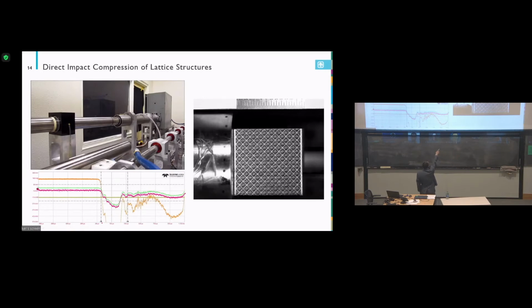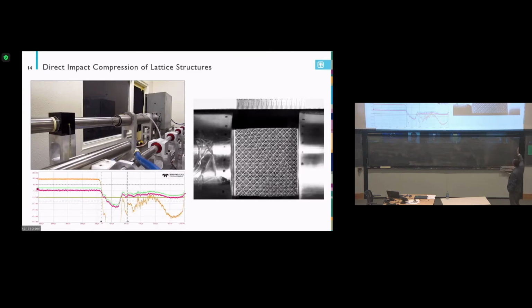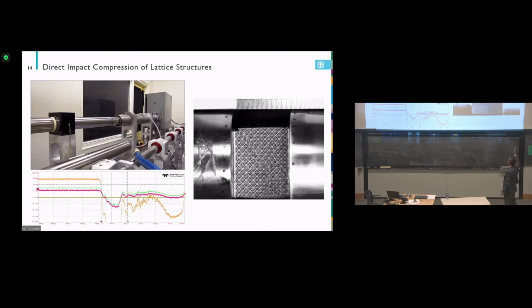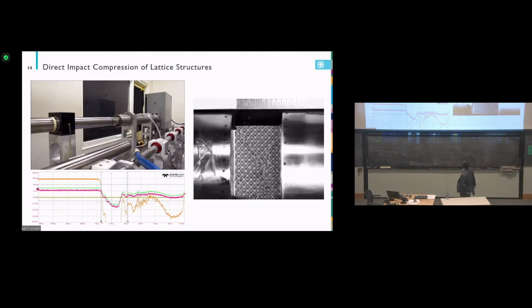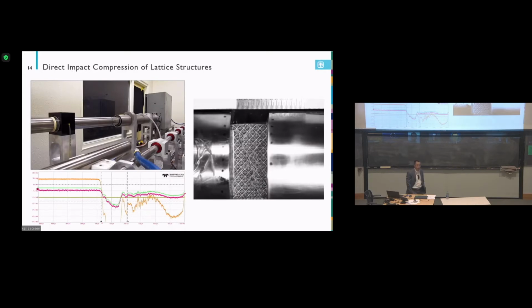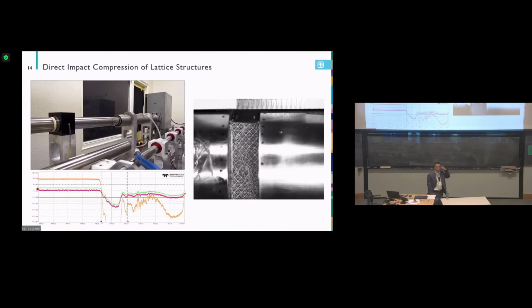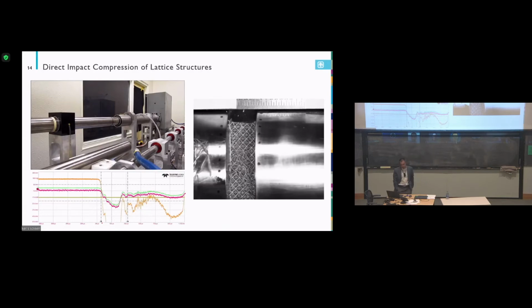Here is an example of how the lattice structure gets fractured during the impact. In this case, we put the lattice structure in front of the bar, so the projectile directly impacts the lattice structure. So you can see how this crushes. The projectile flies in and impacts one surface of this lattice structure. You can see the lattice structure keeps compressing, they get shear fracture and failure, they keep compressing. That helps our material scientists see what's going on. If this failure mode is not what they expected, they have to think about how to change this structure to optimize the performance of the materials. So anyway, that's how we test the lattice structure.